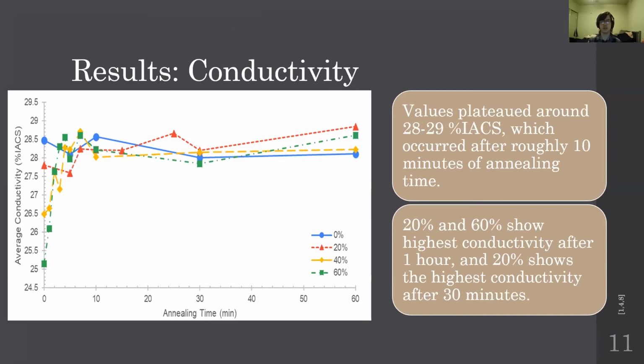You do see here that most of the values do recover to what the unannealed samples were. You see them recover to their natural state, but you also see towards the end, towards the later conductivity annealing times, you see that some of the conductivity values increase.